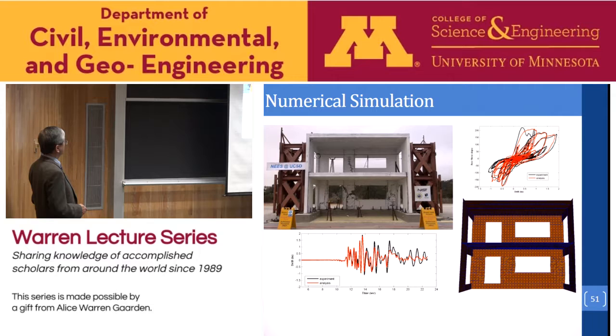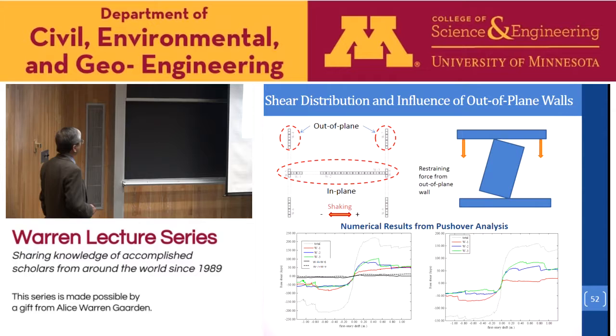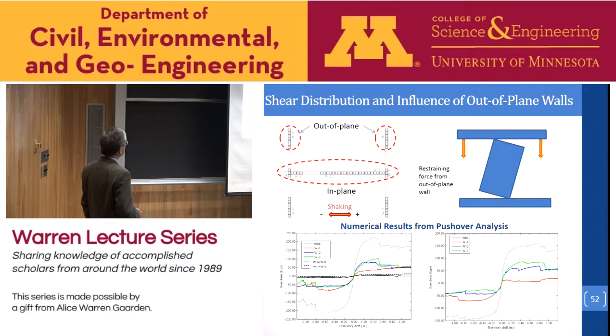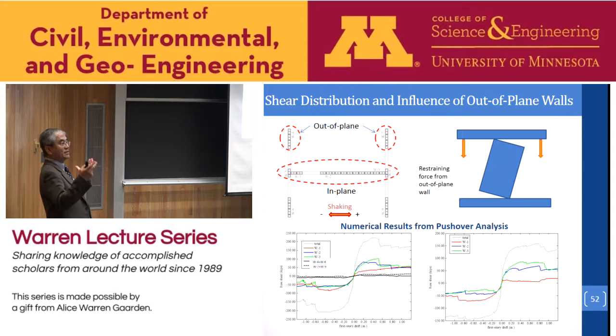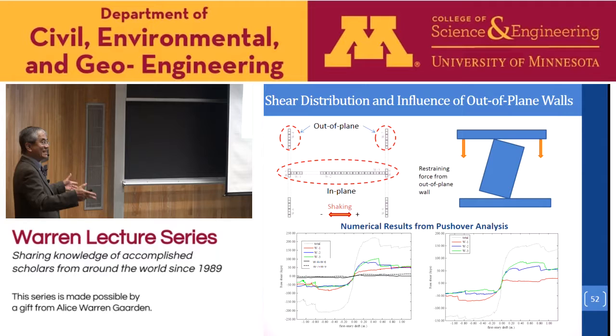So we also use this model to try to understand the system level behavior of these structures. We observe that the capacity of the structure is way higher than one would expect if you just consider the capacity of the in-plane walls. This enhancement is due to the out-of-plane walls, which somehow have a restraining effect. When the in-plane walls rock, as I show here, the out-of-plane wall will be extended and exert additional compression, and that will strengthen the structure a lot.